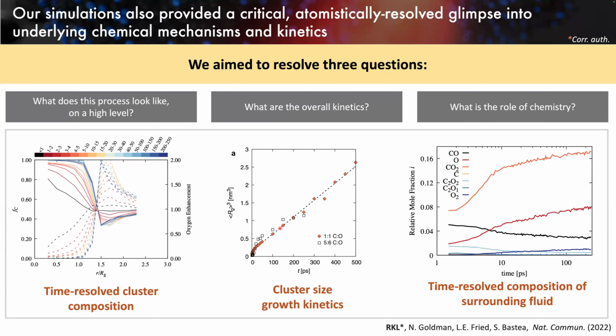So we ran that analysis, and here's what we see. This is now the time-resolved compositional evolution of the fluid solvating our particles. We see there's a lot of carbon dioxide, a considerable amount of oxygen, and a non-negligible amount of carbon monoxide, but we're really not seeing any free carbon in here. It's basically zero. So this is suggesting that carbon transport mechanism is likely reaction mediated.